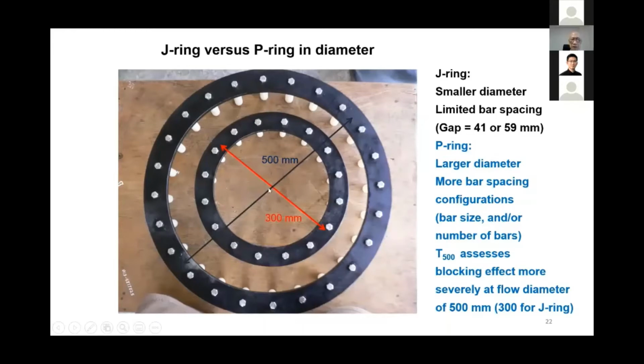So the time taken for the slump to flow after you lift up the slump cone to reach 300 is much, much shorter than to reach 500. In effect, the time to reach 300 is so short that ASTM say don't even use it because it's so uncertain. We are talking about 3 to 5 seconds.